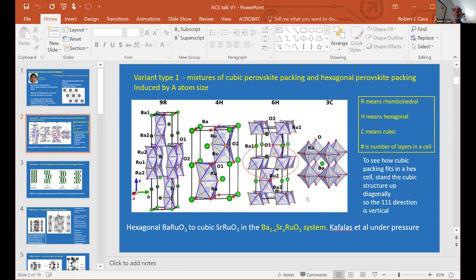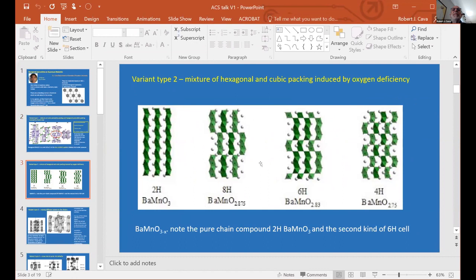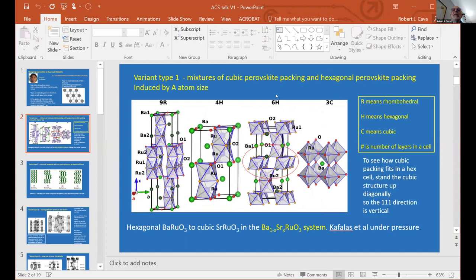So we've got slide number two. Slide number three is something that I think has never been confirmed, but it's kind of crazy. So the first thing I want to say is hexagonal perovskites are a remarkable series of compounds because of the different number of variations you can have. And variation type one is changing the ratio of purely hexagonal layers, which give you face sharing octahedra, and things that are more like cubic layers.